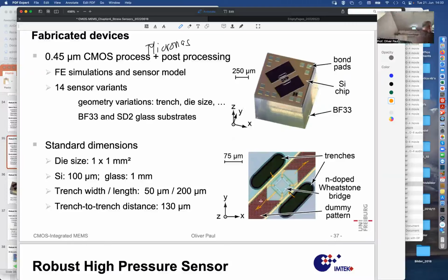Yeah? If there is a bending that causes a longitudinal tensile stress, then this long structure acts a bit like a beam, yeah? And then it would like to contract like any beam does if you pull it along. Of course, it's not a complete beam because it still rests at the bottom. The silicon is bonded to the glass. So the bottom surface of that silicon structure here still rests on glass, just like all the silicon that you see around here. And here you see into the black hole, and where do you look at? At the glass. Now, why is it black? I don't know, some optical microscope effect. You should see through, actually. Or maybe there was some remainder of silicon still there. Then it's maybe just dark because you're looking into a black hole. But anyway, so this anisotropy we can see now with those arrows as well.